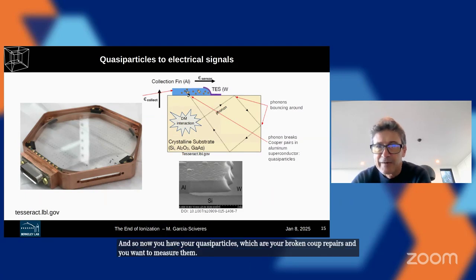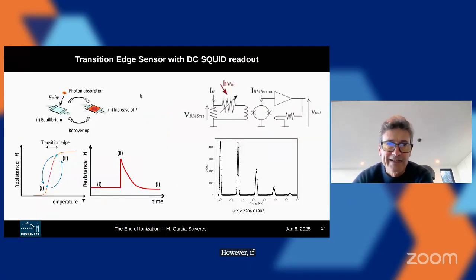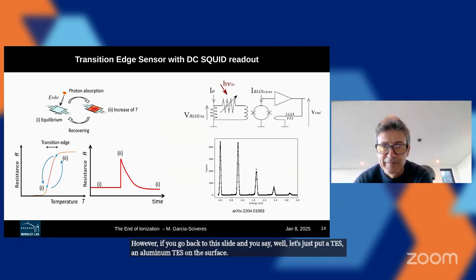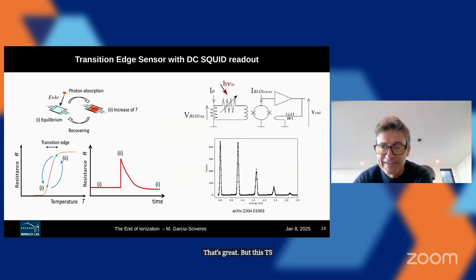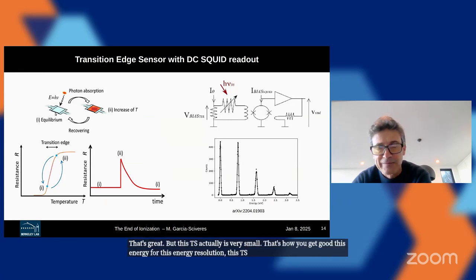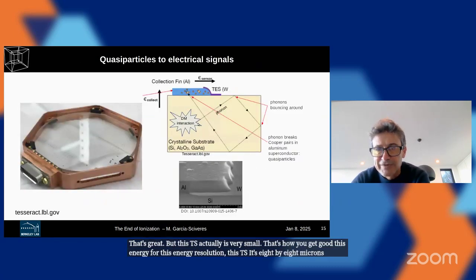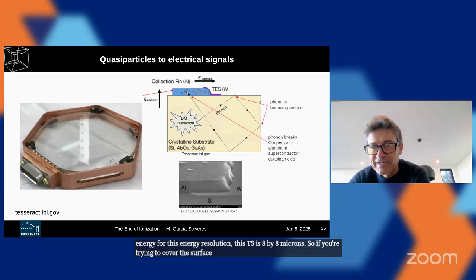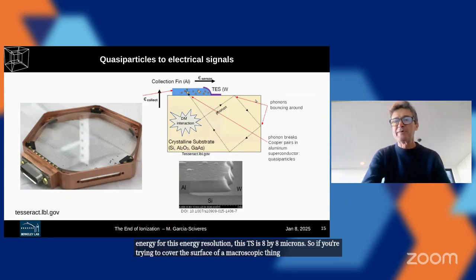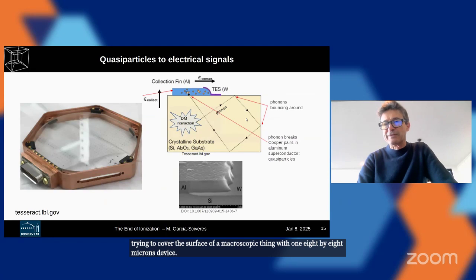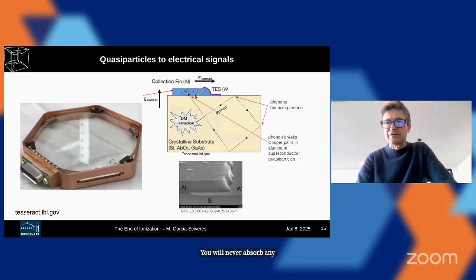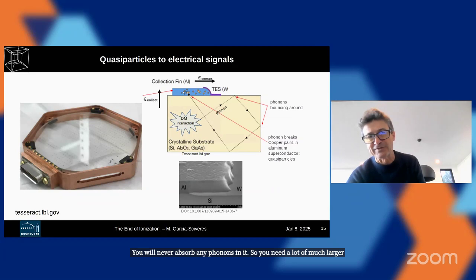However, if you go back to this slide and say, well, let's just put an aluminum TES on the surface, that's great. But this TES is actually very small. That's how you get good energy resolution. For this energy resolution, this TES is 8 by 8 microns. So if you're trying to cover the surface of a macroscopic thing with one 8 by 8 micron device, you will never absorb any phonons in it. So you need a much larger amount of material to absorb the phonons.